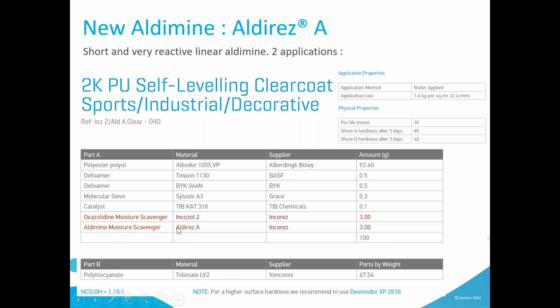In this case, Aldirez is used in the part A. We also added some Incozol 2 to dry the system first. The reason being is that you want the Aldirez to stay unblocked into your part A so that it starts reacting only once the part A and part B are mixed together. And thanks to Aldirez, this type of system can cure in 1 day only, while without it, you would never achieve a drying. You would need probably to apply 2 or 3 layers.